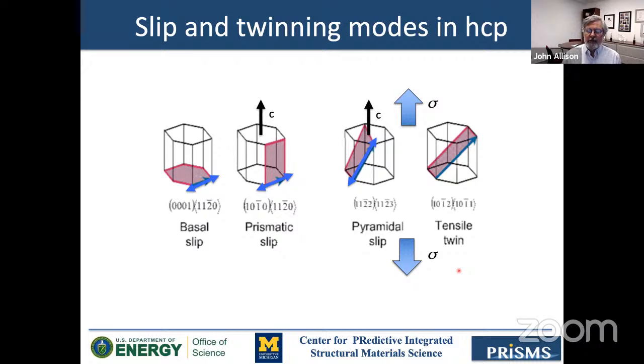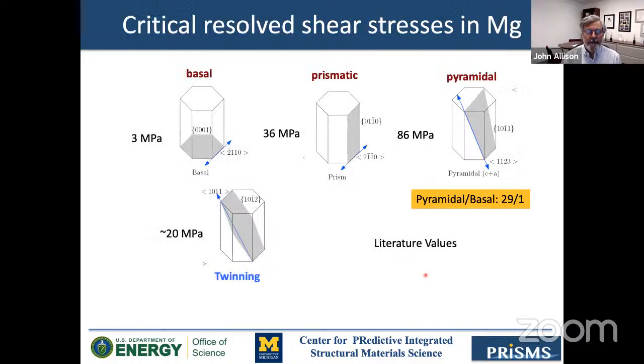So if we have tensile stresses along the C-axis in a particular grain, then these slip modes can be activated if everything is set up right for that. To look at the literature, if you will, of the critical resolved shear stresses in pure Mg and unalloyed Mg, this is kind of where we think we are in the literature. So this basal slip is around 3 megapascals, 36 MPa for prismatic and 86 for pyramidal.